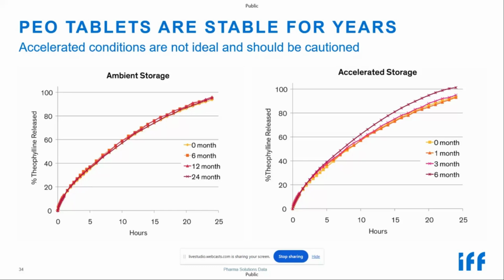We put those same tablets in accelerated storage conditions and measure dissolution at 0, 1, 3, and 6 months. And again, up to 3 months, we're seeing really good dissolution profiles. At 6 months, accelerated storage conditions, again, that's 75% relative humidity and 40 degrees Celsius, we're starting to see a little bit faster release profile, indicating that there's potentially PEO degradation. I'm not too surprised with this because those storage conditions are so harsh for PEO, and now we're just pushing the limit of the auto oxidation inside that tablet.